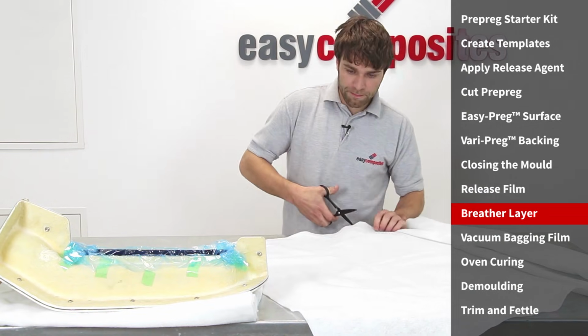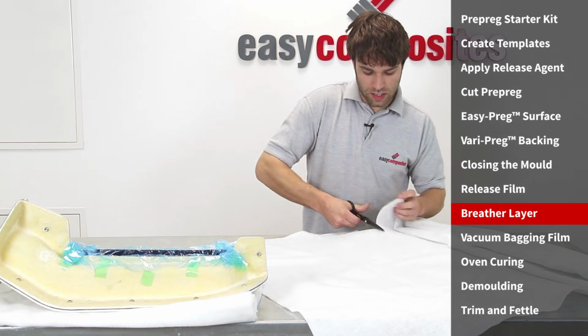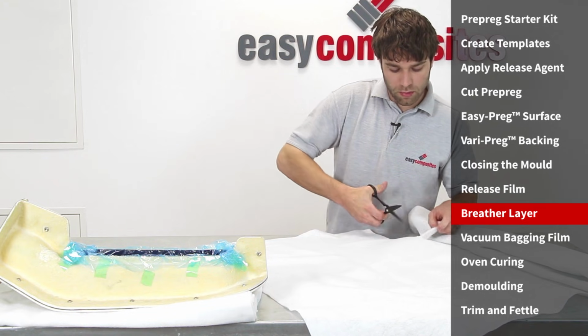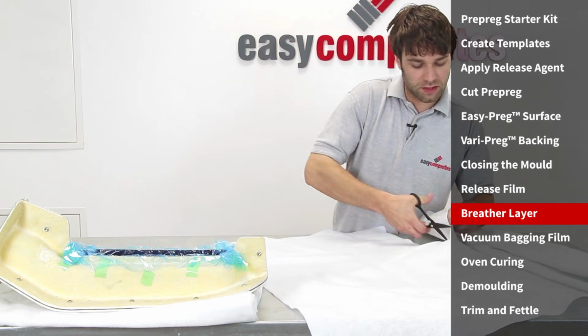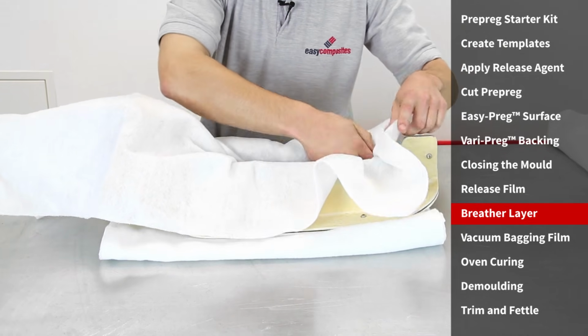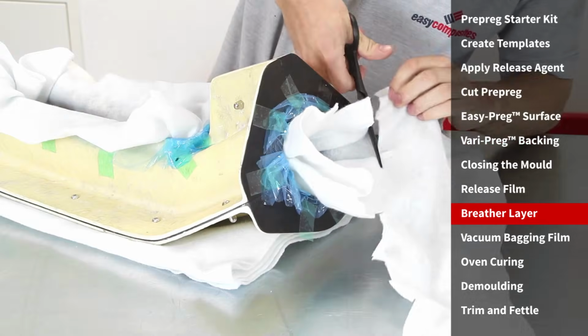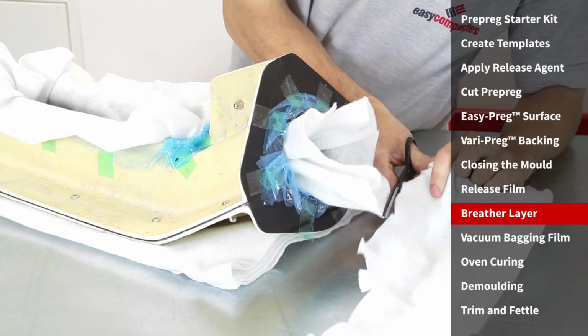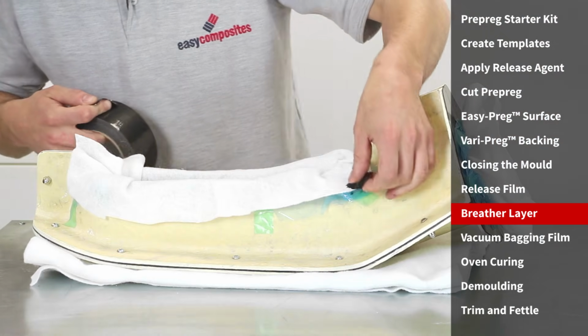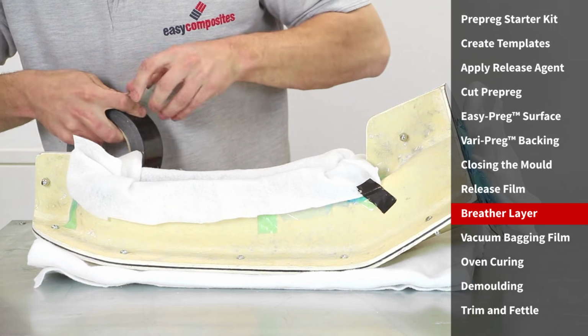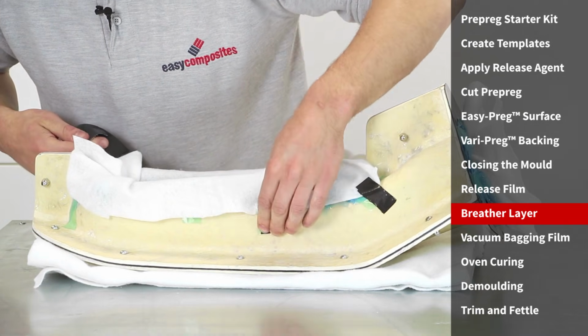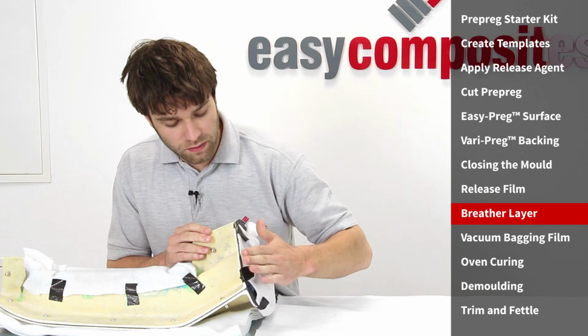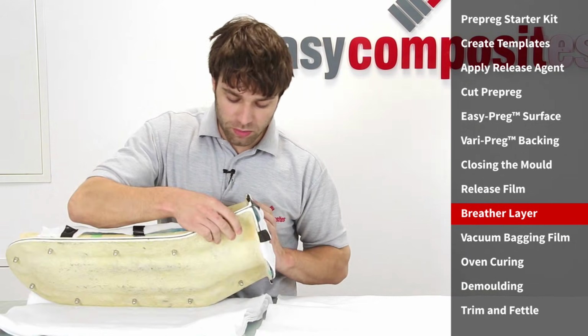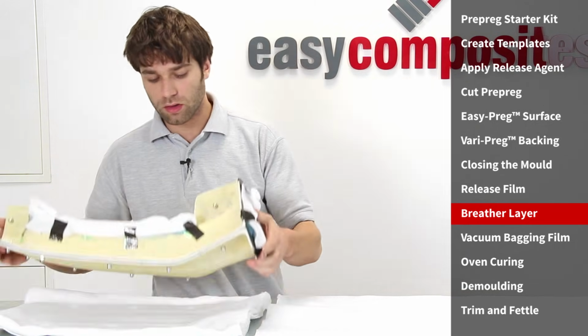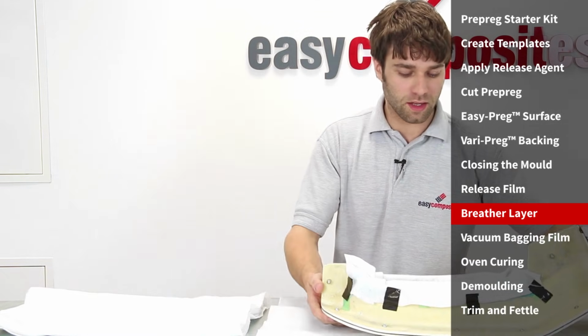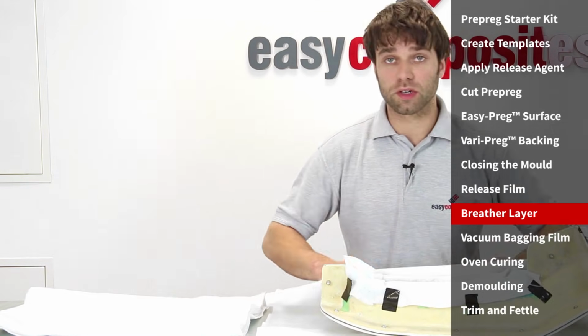So now we're onto the breather layer, which again we're going to put into the mould in just the same way that we did the release film. The breather cloth is there to maintain air paths through the bag. It should be positioned across the whole surface of the mould and then held in place with some tape. To eliminate the chances of any of these sharp mould edges or the bolts themselves puncturing the bag, we're also going to wrap the back of the mould in some breather, and this will offer a reasonable degree of protection.